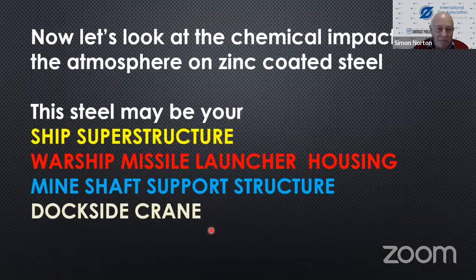Now, this steel might be your ship superstructure. You have zinc thermally sprayed it, or it might be a warship missile launcher housing, and it's been zinc thermal sprayed, maybe even zinc-rich paint coating. Mine shaft support structure. You didn't galvanize it, but you decided you better protect it, so you called in spec coats and they carried out zinc-rich paint coating. Or a dockside crane where during maintenance you used either zinc thermal spray or zinc-rich paint.